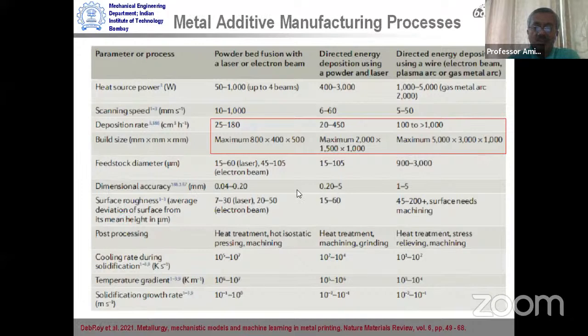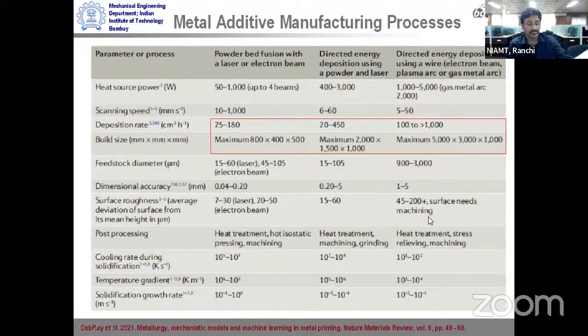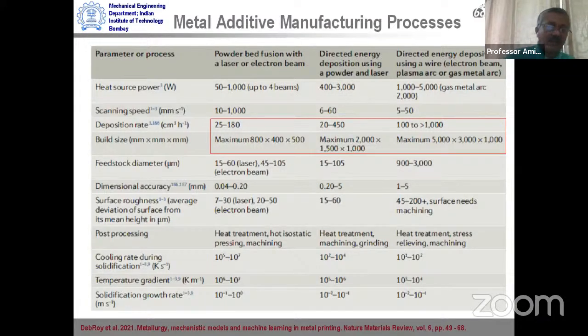So this would be typically, as of now, the reported results from the literature. Of course, it is intuitive that in a directed energy process with arc and filler wire as the feedstock, because it has a slightly higher diameter compared to powder diameters, it will have a rougher surface. So post-processing is required in this kind of process. In contrast, if we talk of powder bed fusion, where powder sizes are much smaller, we will have much better surface quality. So this is more or less known. But as of now, these are the kind of numbers reported in the literature.